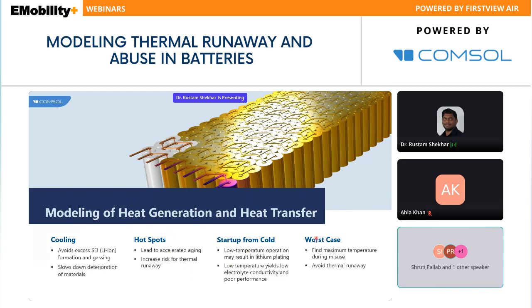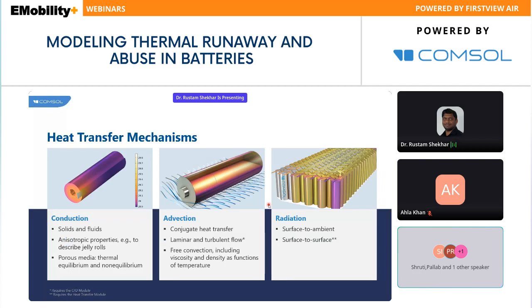And in some cases, when we fail to avoid the runaway, then in this case we will see the maximum temperature and avoid thermal runaway. So once we know and are able to replicate the behavior in the worst case scenario of thermal runaway, then we can design some strategies to prevent the thermal runaway. Now we talked about heat transfer. Heat transfer can come into the picture in three different ways: conduction, convection, and radiation.